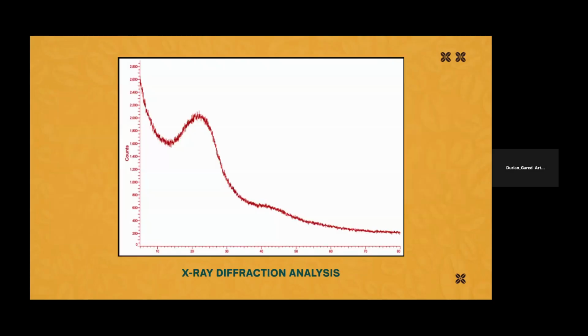Then these findings are further corroborated by the X-ray diffraction results, which confirm the successful synthesis of GOQDs by revealing structural features characteristic of an amorphous or nanocrystalline material. Specifically, the XRD patterns show a broad peak centered around 24 to 28 degrees at 2 theta, which is commonly attributed to reduced graphene oxide, or GOQDs. This broad peak indicates a disordered nanostructured arrangement consistent with the fragmented and non-crystalline nature observed in the previous test.